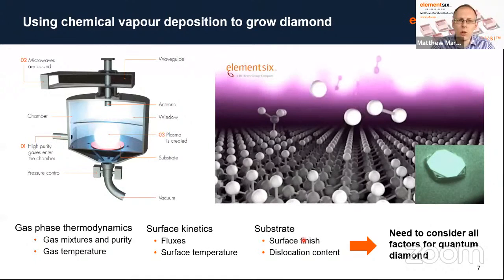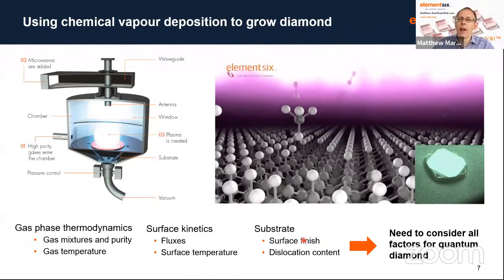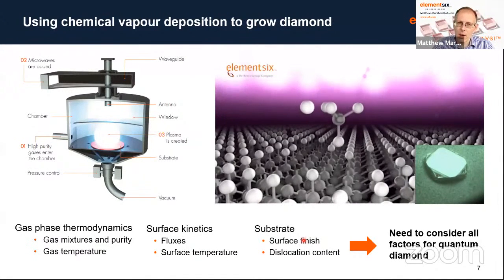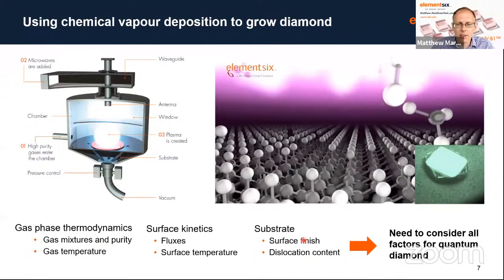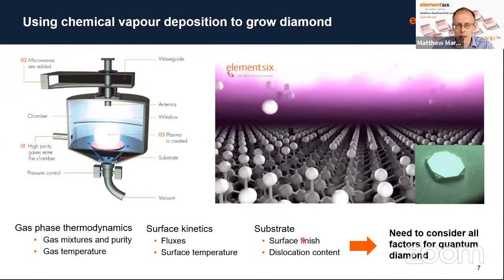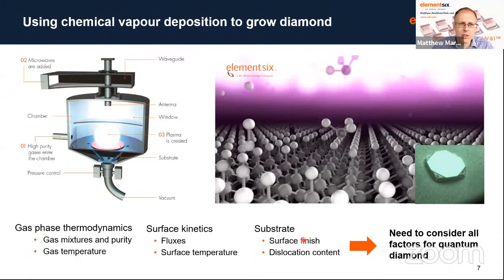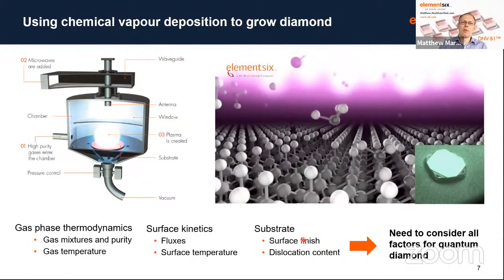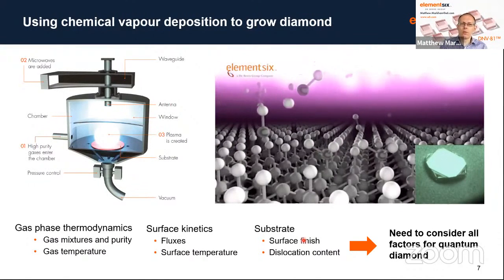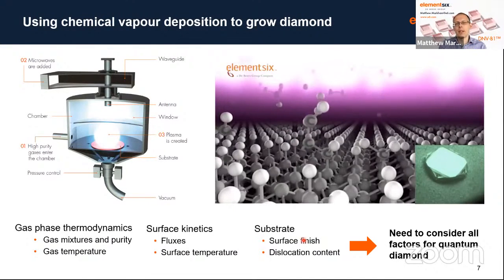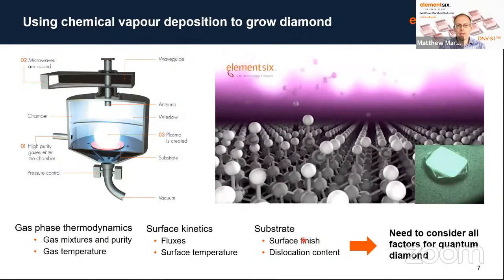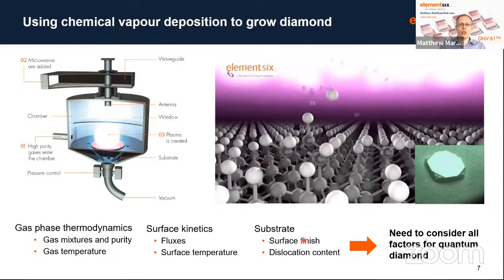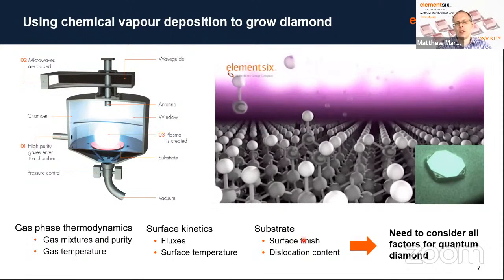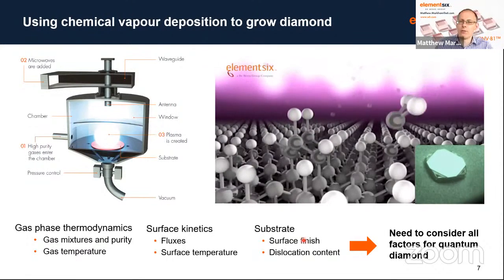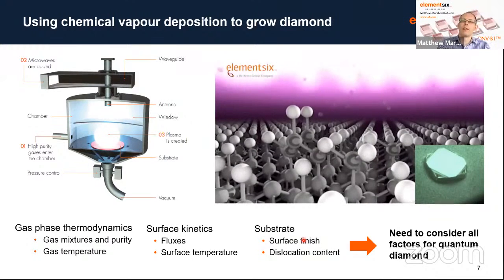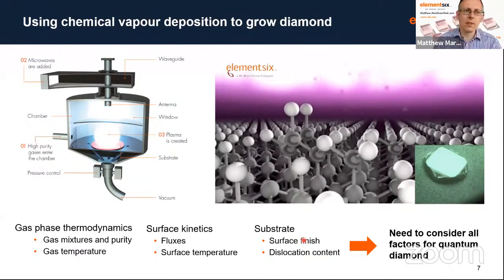So we use a process called chemical vapor deposition. We do also have high pressure, high temperature in-house. That's what my colleagues in the abrasive sector use. However, the reason chemical vapor deposition is quite key for quantum technologies is you have much better control over the inputs into that process, so that you're able to tune things like the nitrogen concentration in the material, and therefore the NV concentration, as well as things like the isotopic purity of the material.